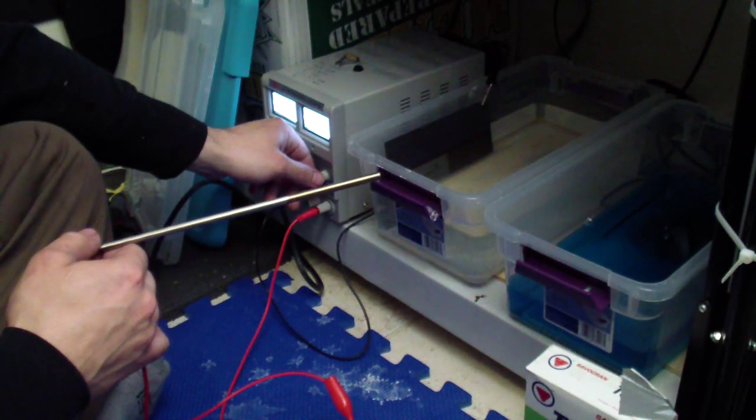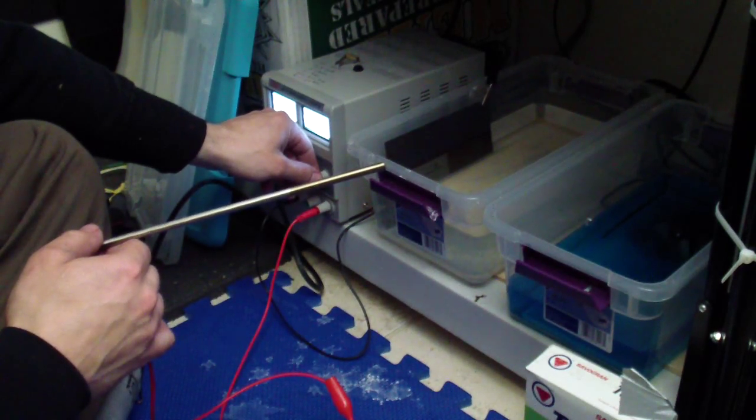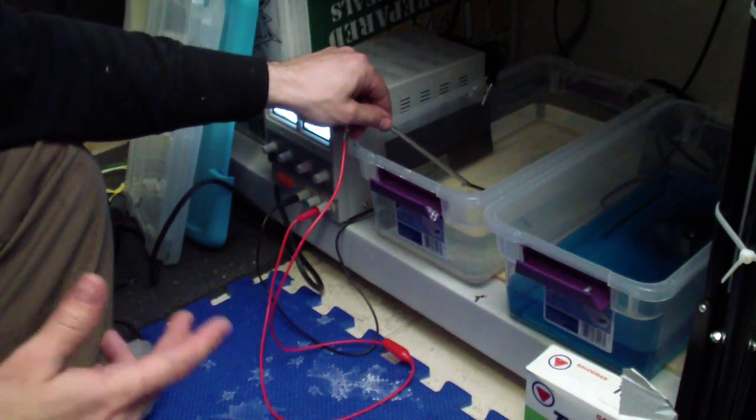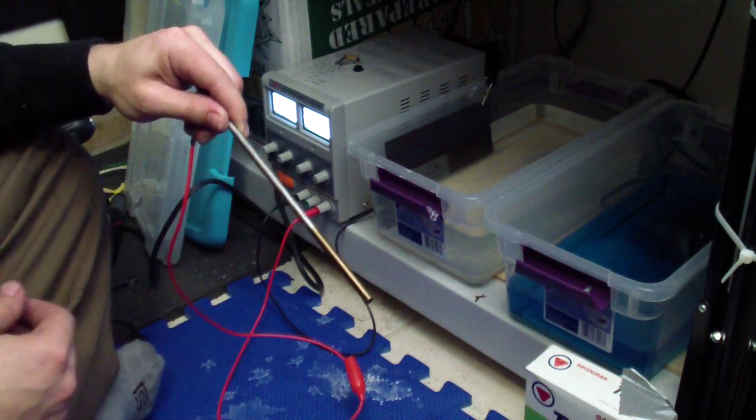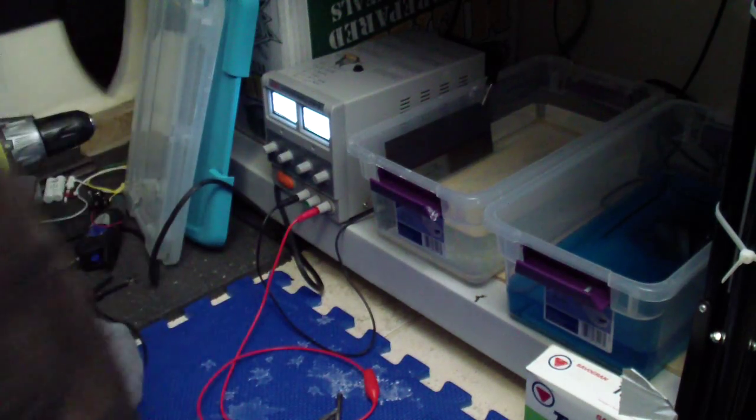Let's say another one. I'm just going to keep changing the voltage and it will keep changing the colors. 13.8 volts. The higher voltage will always change the color on the lower voltage. That's actually the next trick I'm going to show you, that's how you do the two tones.